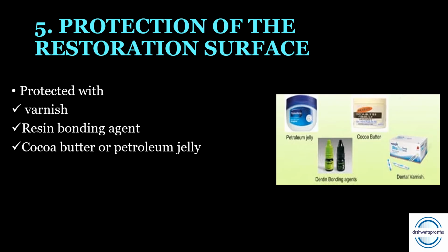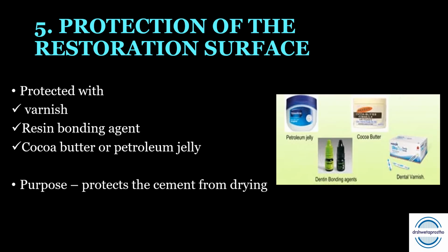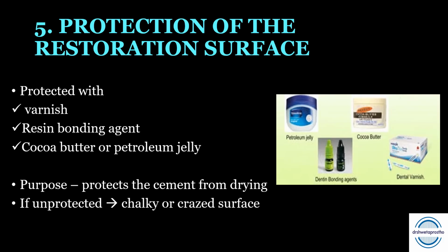Now why is this protection done? This protects the cement from drying while we are doing the finishing procedure. Otherwise, what will happen? It will lead to a chalky or crazed surface. So it should be protected after the restoration is complete.